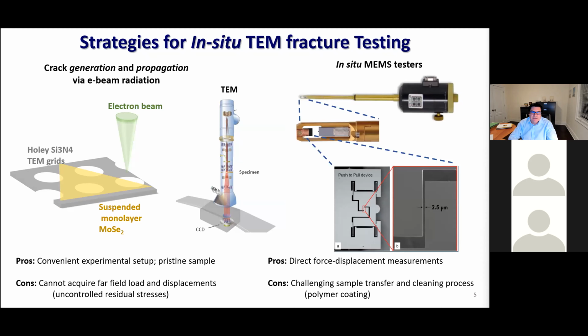Let me start by sharing with you some of the heroic experiments, as described by one friend at the National Lab. If you try to do in situ transmission electron microscopy experiments of fracture, there are essentially two approaches that the community is following. The one on the left consists of depositing one of these flakes on a grid that has holes. The grid is basically a silicon nitride membrane. And so you can have electron beams in a transmission electron microscope, like illustrated here with the location of the specimen, and then in CCDs get information about the atomic configurations.